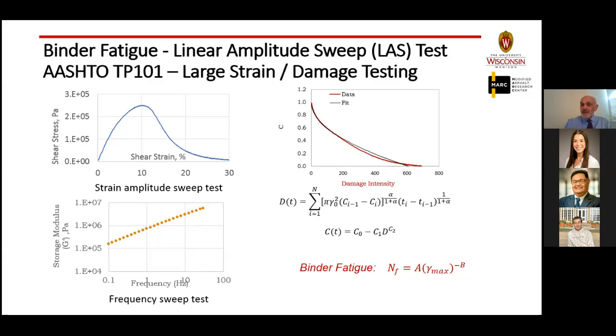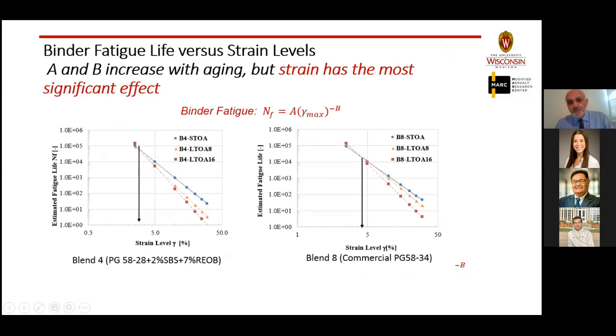This is the same machine, the DSR, and all we did is tell the machine to increase the strain until we see the failure behavior. And by taking this, and applying the viscoelastic continuum damage, we can actually determine A and B as a function of the strain level. So what do we get out of this, which I call the strain amplitude sweep, or the high strain test, if you will.